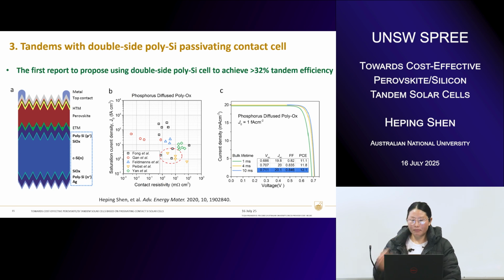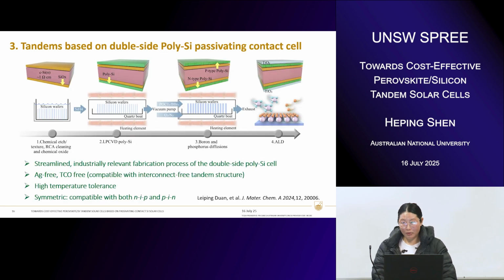At that time we demonstrated over 32% efficiency tandems using this structure based on the NIP cell structure we established in our lab, and proposed the possibility as well as the strategies for achieving that. Inspired by that, we then focused in the lab on developing such a structure using industry-relevant processes. If you look at this bottom double-sided TOPCon cell structure, that is the final structure we use, where you can see the silicon wafer, and on each side, one is n-type poly and the other is p-type. It's very like a heterojunction, but it's a TOPCon passivating contact.